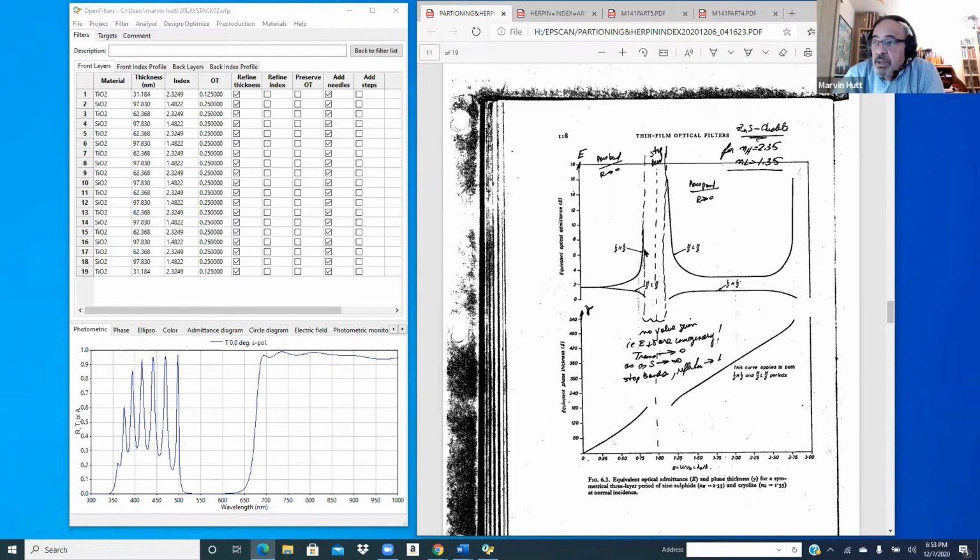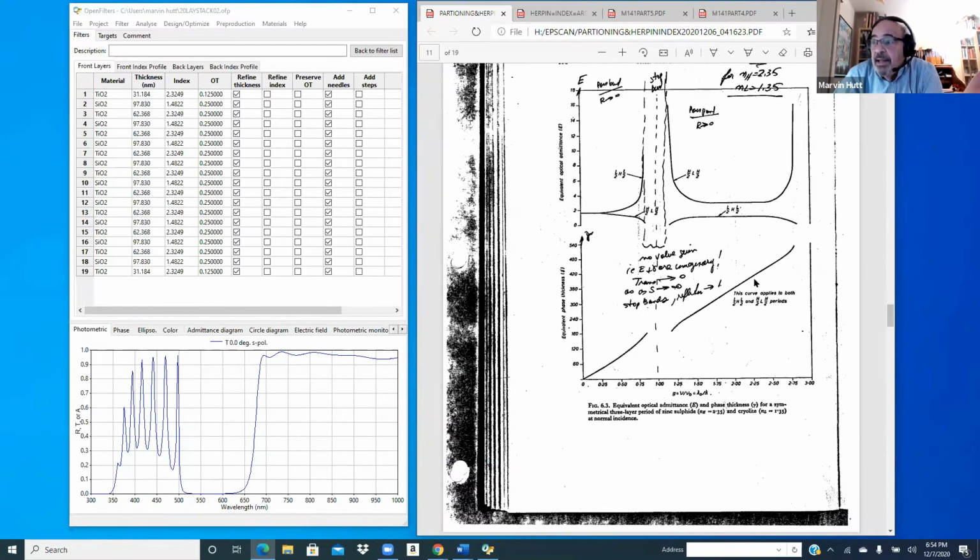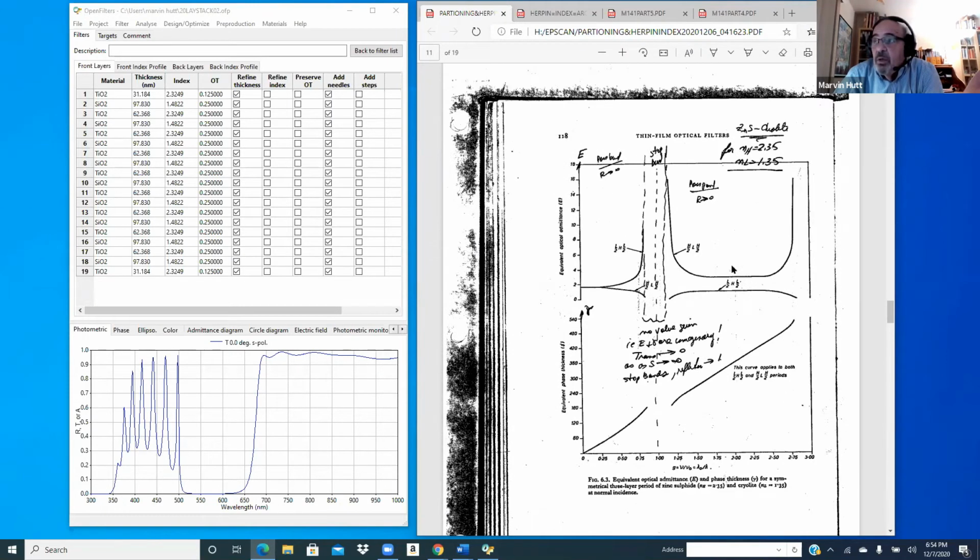This envelope here, for low, high, low, bounds between, means that the oscillation in here, if the index of the base material is 1.5, then the oscillations are going to be between that and this. And then on coming down between this and that in this area. Okay? You follow? So isn't that terrific? In one shot, just by calculating LHL, you get this curve out.